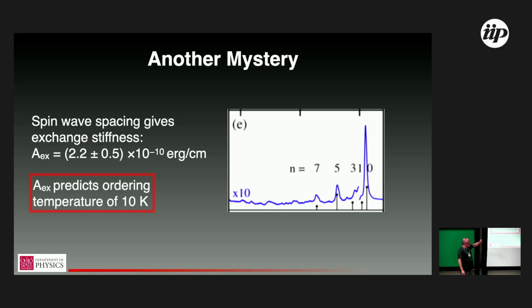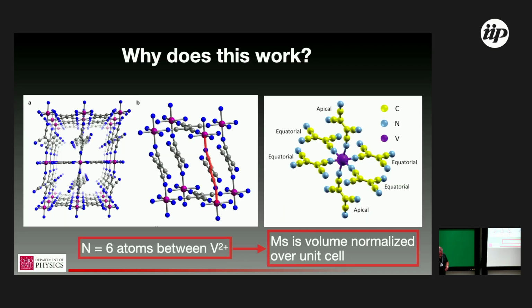Then there are a number of heuristics that link A_ex, the exchange stiffness, to M_S, the saturation magnetization, and therefore you can use that to predict the magnetic ordering temperature, and we get 10 Kelvin, right? Which in one sense is reassuring for skeptics in the audience who, on seeing the crystal structure at first, said that should not be a good magnet. This would argue, yeah, it's not a very good magnet in the sense of being strongly ordered, but that's in direct contradiction to the experimental observation of the high T_C. So why does this work?